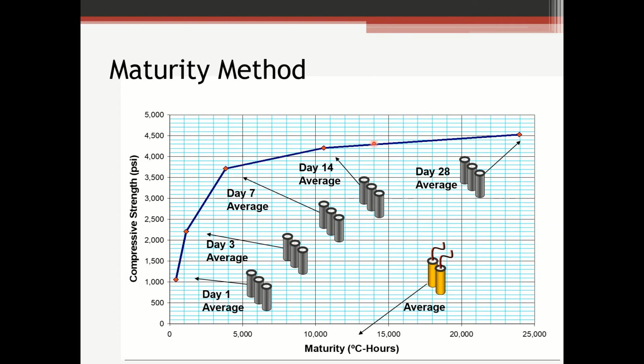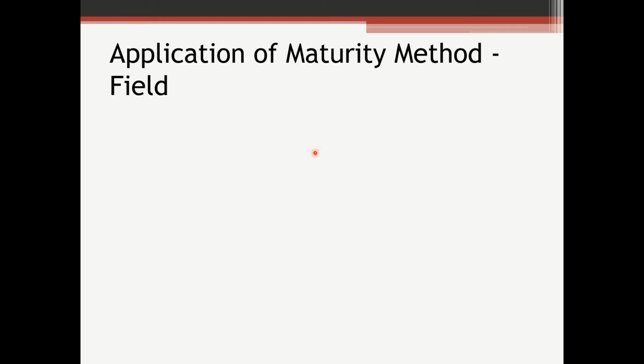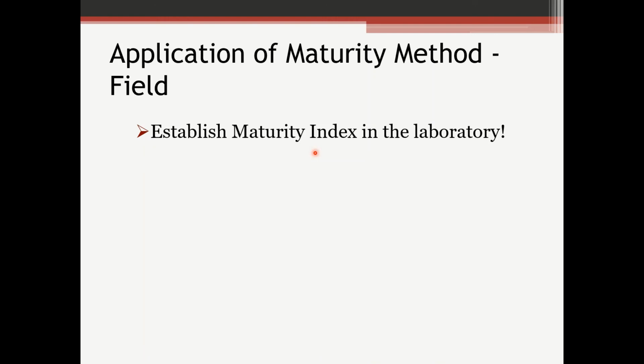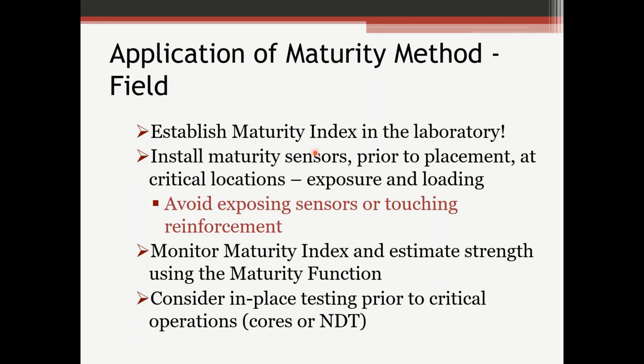And you apply this in the field by measuring what your maturity value is in the field. If you've got 10,000 degree hours in the field, that's what you measured in the field, then theoretically you've got about 4,000 psi on the structure. Again, we're doing this first in the laboratory. These are the maturity functions. Those graphs are specific to the mix.